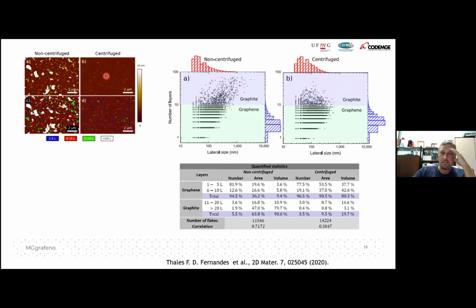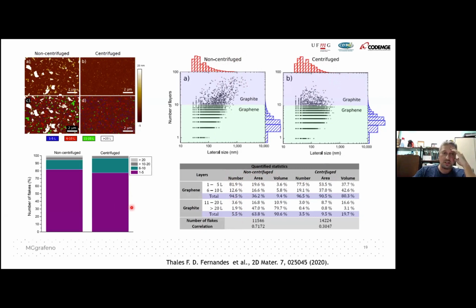So what's the problem with these measurements? Because they are really statistical measurements. So why do they look so alike, when they are completely different materials? The problem here is in these numbers: you have statistics of number, area, and volume. If you look at the statistics of numbers, which is pretty much what everybody does, or almost everybody does, you don't see much difference.